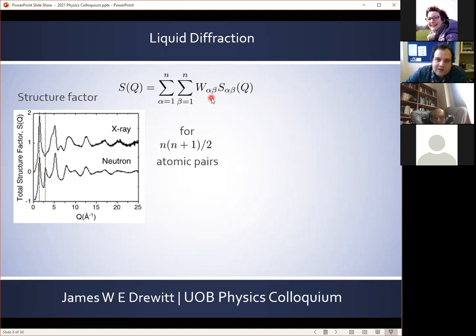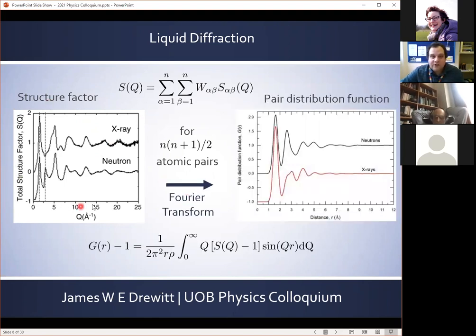And the weighting factors on these individual pair correlations are different depending on whether we use X-rays or neutrons. So the X-ray form factor, for example, increases as a function of atomic number, so we probe heavier elements much more strongly, whereas with neutrons it's possible to probe light elements, including hydrogen and oxygen. And so the two techniques are very complementary. We can Fourier transform our total structure factor to obtain our real space information in terms of the pair distribution function, which gives us essentially a probability distribution of finding an atom at a distance r from another atom centered at the origin.